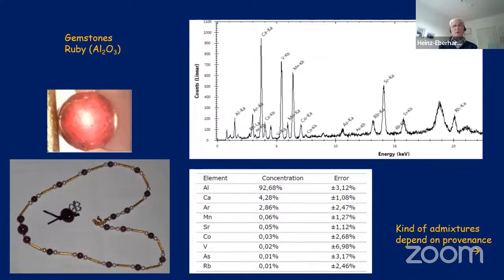Ruby gemstones in bracelets, for example. Ruby typically is aluminum oxide. Aluminum has a Z of 13, which is at the edge of easy detectability. And that you can see in this spectrum here. The aluminum K line is here. Although the basic component in ruby is the aluminum oxide, more or less 100% aluminum, we only see very little K X-rays coming out. That is because of the fluorescence yield, the competition between X-ray radiation coming out or electron emission. So that's why we have such a low intensity in the aluminum K X-ray.